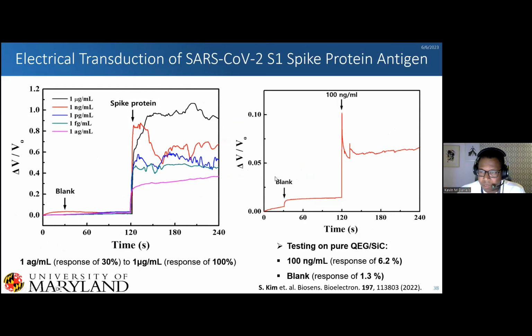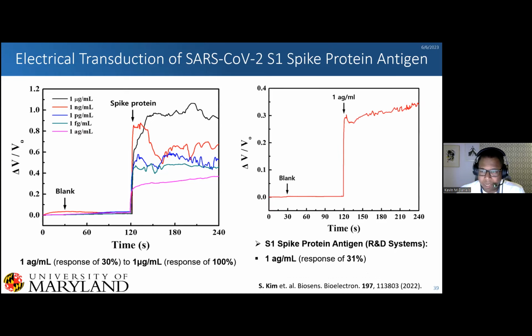We tested our sensor with just bare graphene. So this is pure graphene, and we put down 100 nanogram per milliliter on top, and we only got a response of 6.2%. Putting down an attogram, so many, many orders of magnitude less, we get a response of 30%. And so we know that this is an effect of binding, not just some transfer of ions in our solution. And as you can see, to an attogram per milliliter, we get a really, really fast response. So again, in a second to less than a second, we get a pretty fast response, letting someone know, okay, well, you possibly have the virus, well, not possibly, but do have the virus. We have to say possibly because this device is not FDA approved.